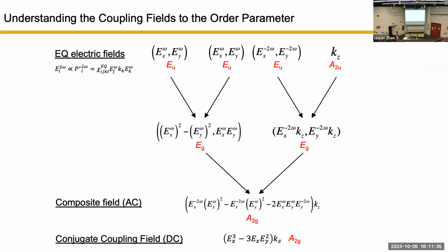We are using the so-called electric quadrupole process to do this measurement. For the electric quadrupole process, we have four vectors participating: two copies of the incoming field, one copy of the outgoing field, and one copy of the wave vector, because quadrupole radiation depends on the gradient of the field, which is essentially the optical wave vector. These four copies combined together form a form that has exactly the right symmetry as the so-called ferrorotational order. Any fewer vectors cannot construct the right symmetry.